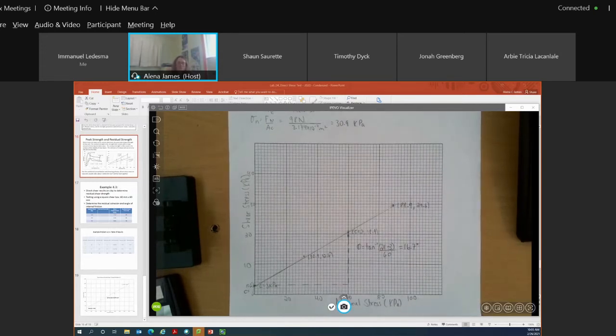Good cohesion value for clay? Well, Conrad, it typically varies, but we see anywhere between about 2 and 8 kPa for the lacustrine clays in the Winnipeg area, generally in the 2 to 5 range if they're at their residual values. Our standard shear strength values for clay along riverbanks are 2 and 10: a cohesion of 2 and a friction angle of 10. At post-peak values, if we're offset from the river, we'll use a cohesion of 5 and a friction angle of 14. I've seen friction angles go as high as 20 if your material is more alluvial in nature, with a slightly increased cohesion around 5 kPa. Our lacustrine clays in the Red River Valley aren't very strong.